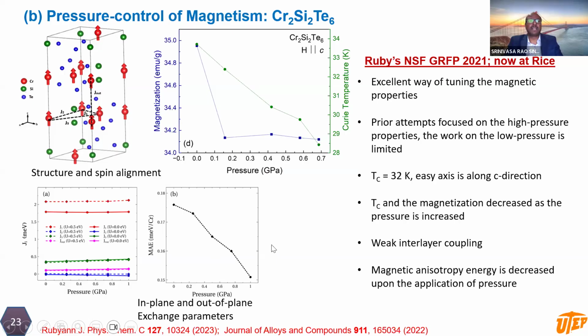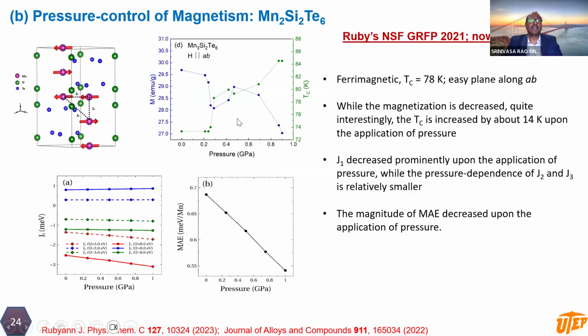This is the one we did on the chromium silicon telluride layered compound, whose Curie temperature is about 32 Kelvin. Then we changed chromium into manganese. The magnetization decreased as a function of increasing pressure. However, the Curie temperature starts increasing as we increase the pressure. So, exactly similar compound, but the Curie temperature behavior as a function of pressure is completely different from the previous compound. And our collaborators did some calculations on pressure-dependent magnetic properties, and they saw that the first neighbor exchange interaction, the J component, changes as a function of pressure, as well as the magnetic anisotropy energy.